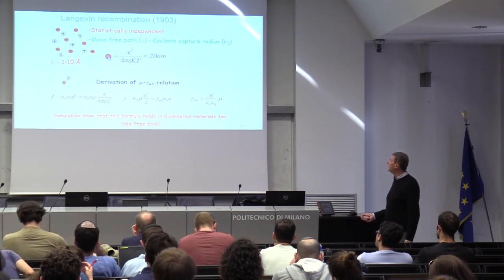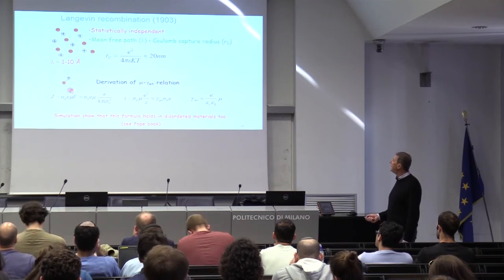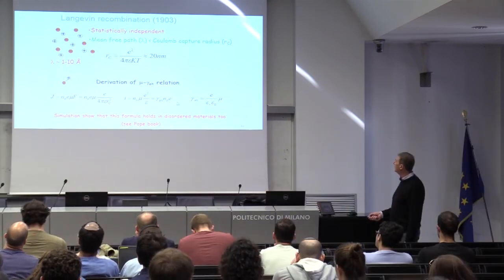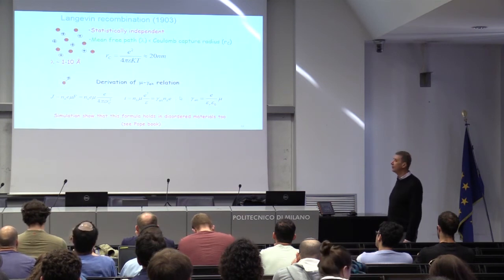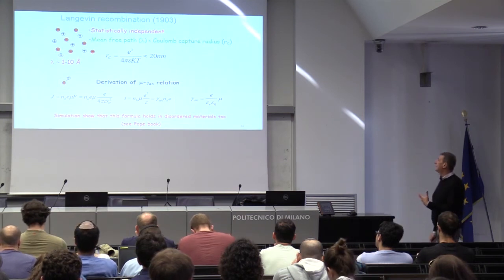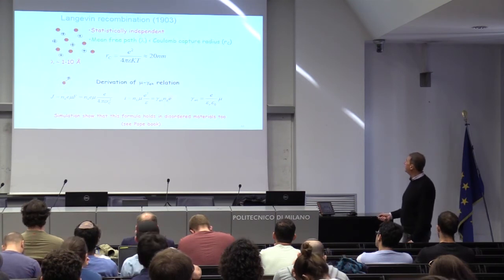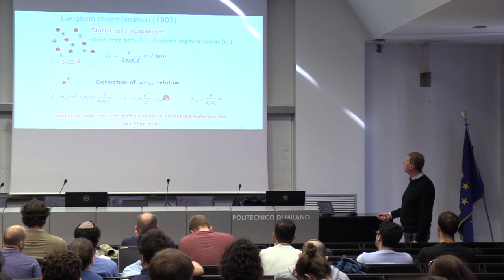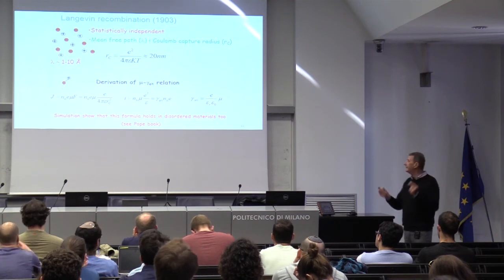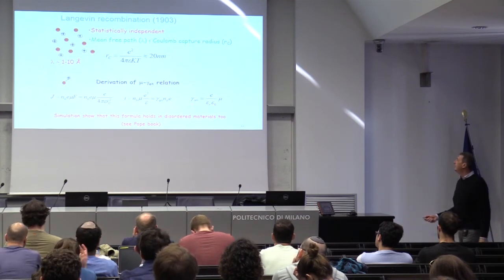So in this situation, the decay of the population is bimolecular. So there is a bimolecular coefficient gamma, which is multiplied by the population to give you a decay. And it depends on the field. And now the nice part here is that the bimolecular coefficient contains the electrical mobility because the charges are moving under the electric field. You see here that the equation is quite simple.